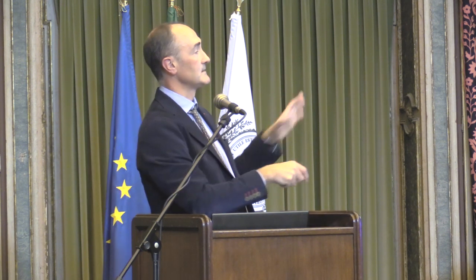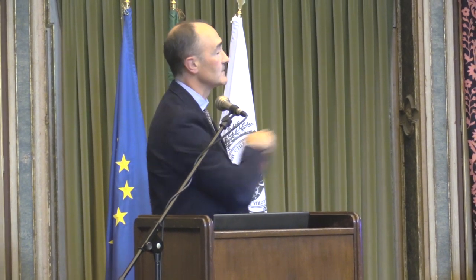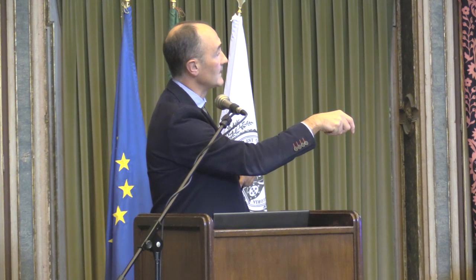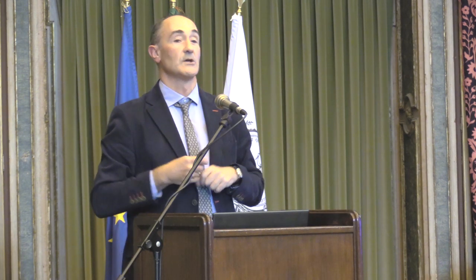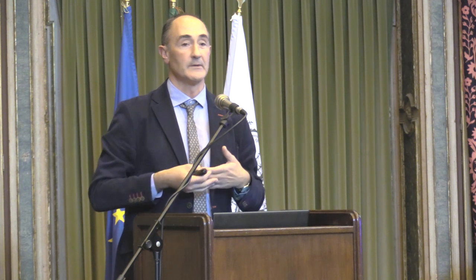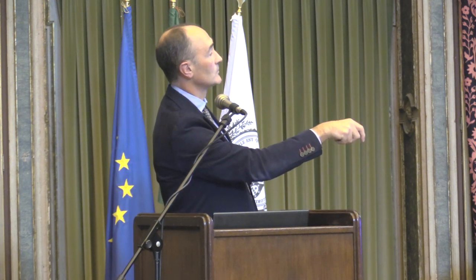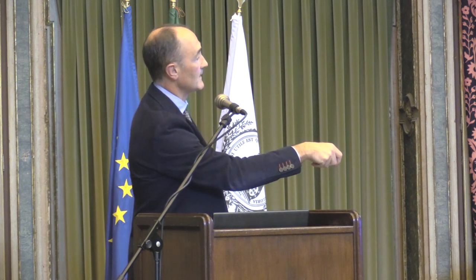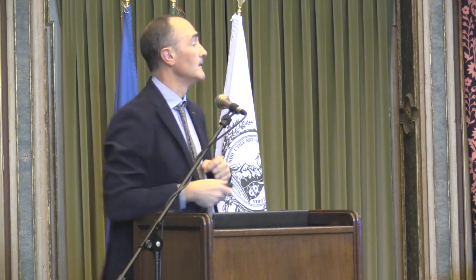In fact, coming back to Professor Balsani's presentation, this is something similar to what he presented for atoms, but now we are presenting it for particles. So we bring, for example, two nanorods close to each other, and we generate bonding and anti-bonding plasmon modes. So you're actually generating a new material with different properties. If you bring particles together in a sort of aromatic fashion, you may have a completely different way to manipulate the electrons in this nanostructure. If you generate helical templates and then you attach your particles in a helix, you will obtain chiral plasmons, and this has been demonstrated.